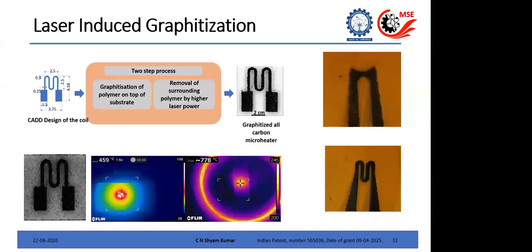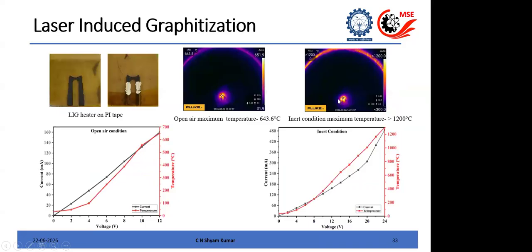And the carbon, as I told, is very stable in inert atmosphere at very high temperature. So you can reach very high temperature. I think we have crossed even that. Now I think these kind of small heaters reach around 1200 degrees Celsius in inert atmosphere and almost like 650 degrees Celsius in open atmosphere. What is interesting here is that if you think of a micro heater, usually it is made with metals, okay, and the process is really labor intensive and costly. You need a mask, you need different deposition systems, and changing the design or changing the size, you need to change the whole process.